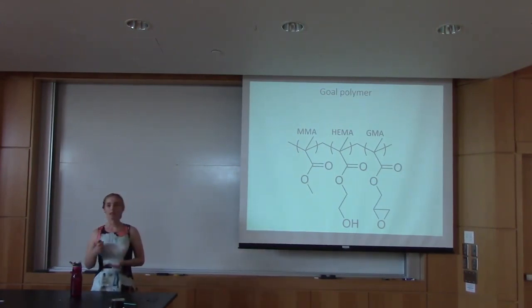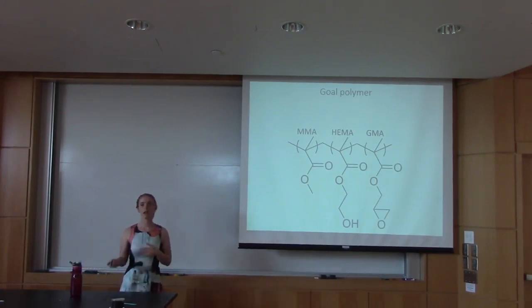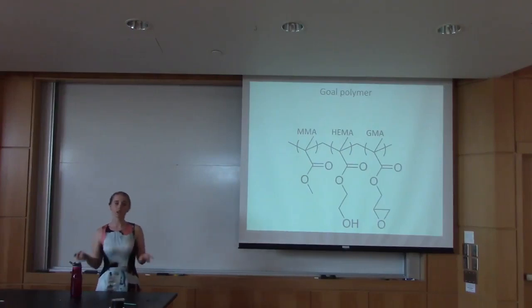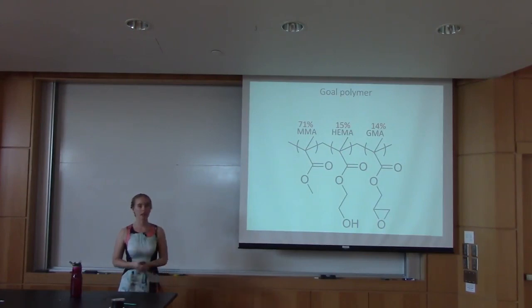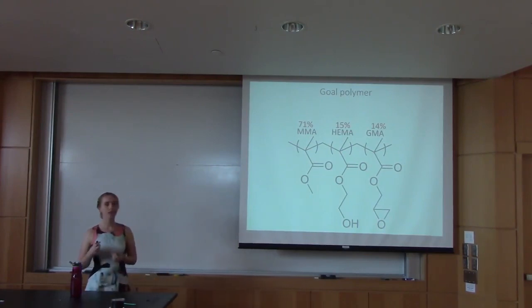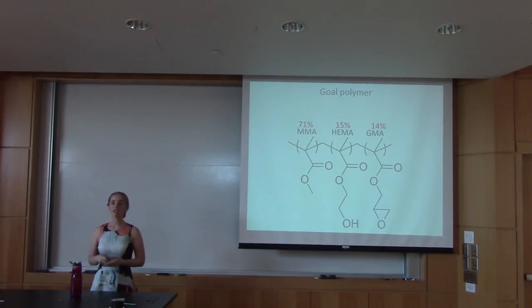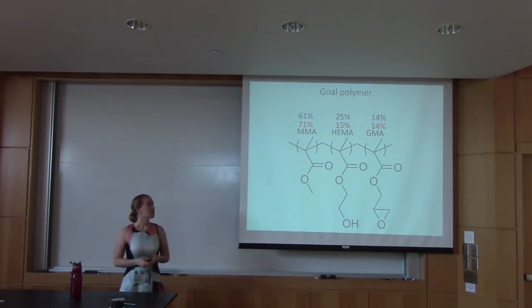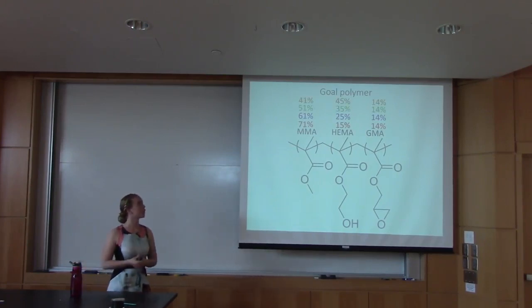And with that, we decided to make 4 different compositions of this polymer in order to test and see when we have a hydrophobic or a hydrophilic or a non-preferential surface. So we started with a 71% MMA, a 15% HEMA, and then a 14% GMA composition. Because our GMA is only being used as a crosslinker, we will keep that composition of the GMA consistent throughout these 4 compositions. Then we have 61% MMA, 25% HEMA, 51% MMA, 35% HEMA, and then lastly 41% MMA and 45% HEMA.